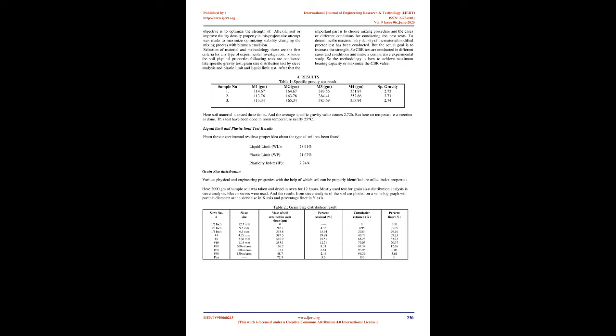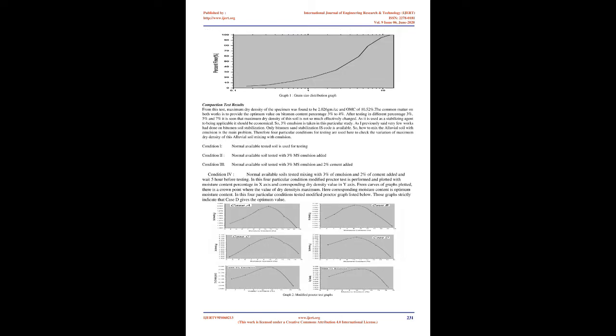Objective of work: The main objective of this study is to improve the properties of the alluvial soil by adding a little cement as filler and bitumen emulsion as stabilizing agent. An attempt has been made to use emulsion for improving the strength and geotechnical properties of alluvial soil. Use of bitumen emulsion is environmentally accepted. The experiments conducted include specific gravity of the soil sample, grain size distribution, liquid limit and plastic limit tests to identify the material, standard proctor test to obtain maximum dry density and optimum moisture content, and CBR test of soil sample mixed with emulsion and cement.